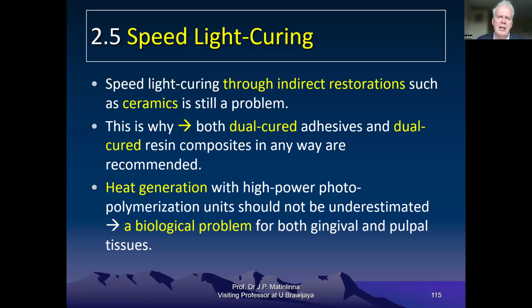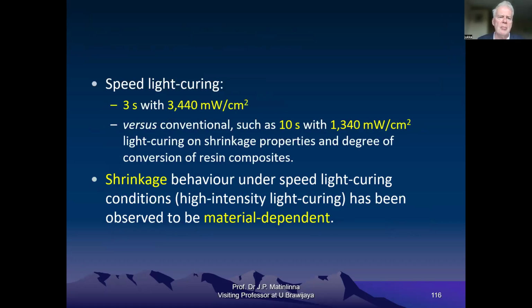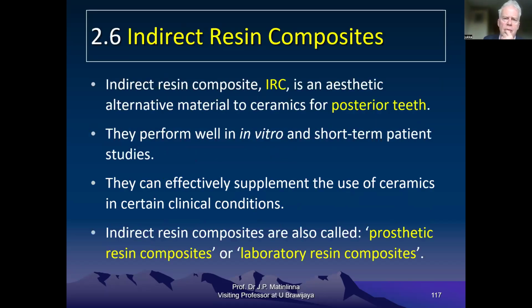So speed light curing is already here, but we should have proper understanding. Is it for light curing resin composite fillings or some of the indirect restorations? We are talking about like 3 seconds with a huge output of energy versus conventional, which is like 10 seconds and 1/3 of the output of the blue light. Shrinkage behavior under speed light curing conditions has been observed to be material dependent, however. This is something new we should keep on following.